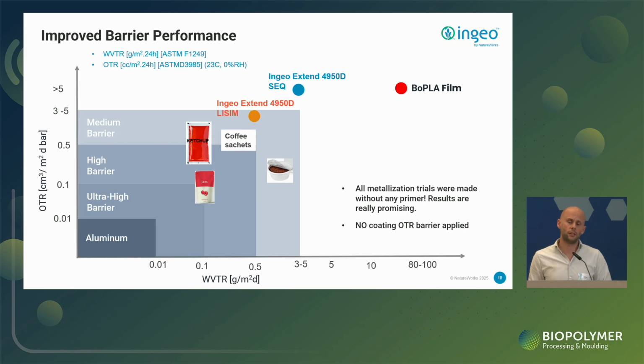Also important to highlight here is that we didn't use any primer. So we have directly metallized the films without using any primer, which is also important for the cost of the product. But also many primers are not compostable certified, so it makes it quite easy for us to be more efficient in that respect. Also, the oxygen barrier is at a reasonable level, but you also have to mention here that the focus so far has been on the reduction of the moisture barrier. In the next step, we will also work on improving the oxygen barrier. The target will be really to achieve barrier levels of, let's say, high barrier or even ultimately ultra-high barrier.